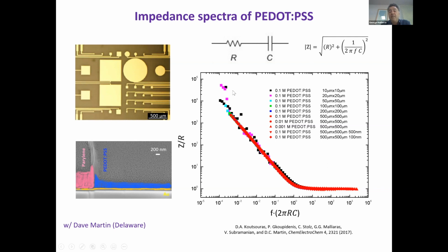And all of this data can be fit with a very simple model where we can account for the electrochemical impedance of these materials by a resistor in series with a capacitor. So if you plot the impedance of a resistor in series with a capacitor, you get this equation. If you divide Z by R and plot the frequency multiplied by this factor, all the curves collapse to this universal one. And here I include characteristic examples of curves with different dimensions of the P-dot film,